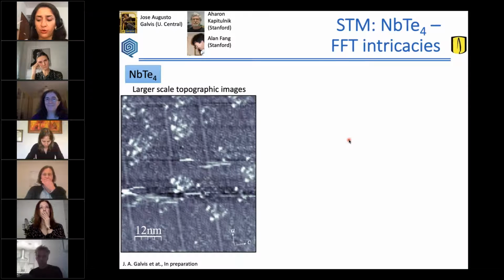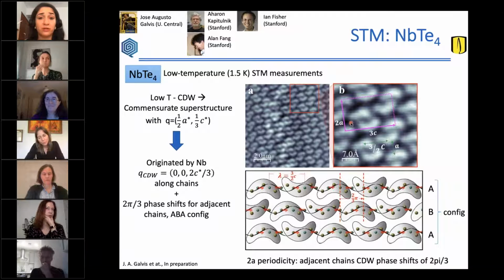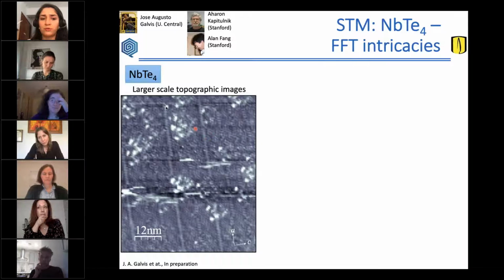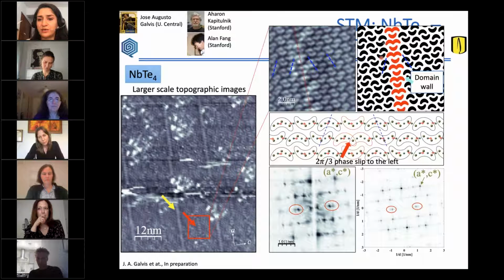And to end this story on niobium tellurium 4, not only were we able to observe these superstructures, which are actually commensurate with the lattice parameter of the material, forming a commensurate charge density wave in this compound, but we are also able to observe that if we take a larger scale topographic image, we see defects in this material which are very extended over large distances. And studying their characteristics, we see that this material is full of domain walls, which makes this material an incommensurate charge density wave instead of just a commensurate charge density wave.